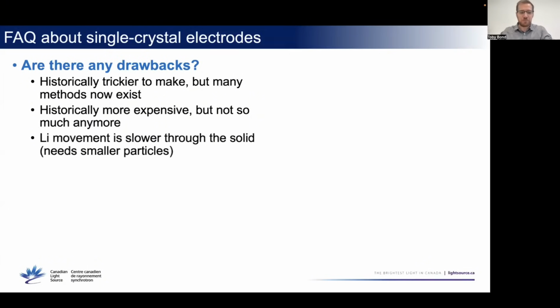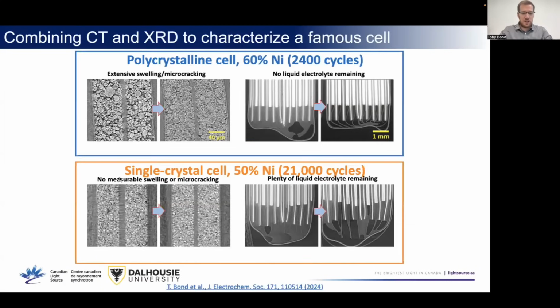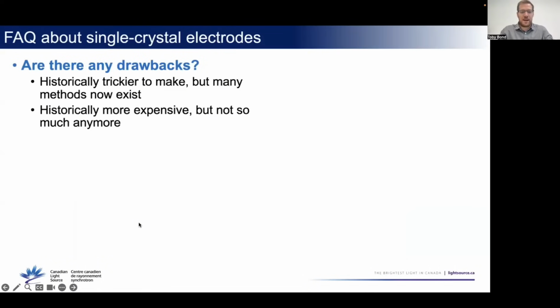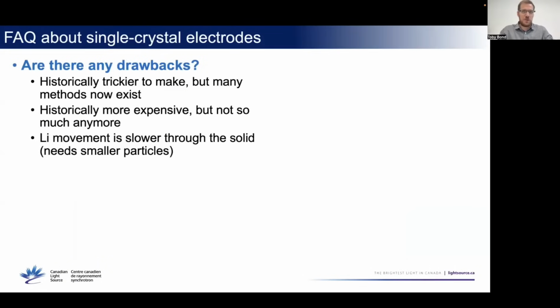for most applications. One other drawback is that because you have these larger particles, the lithium movement is a bit slower. So it moves more slowly through the bulk particle than it does through those grain boundaries. So we have to use smaller particles, and you might have noticed that here, right? These were big particles here, and we use small ones here. So we have to start with more exposed surface area. That's how we can keep the lithium movement through the particles fast. But it's a bit of a drawback. We have to engineer the particles for that. And if you're not doing that, then you'd have a less rate capable material. It wouldn't charge and discharge as quickly.